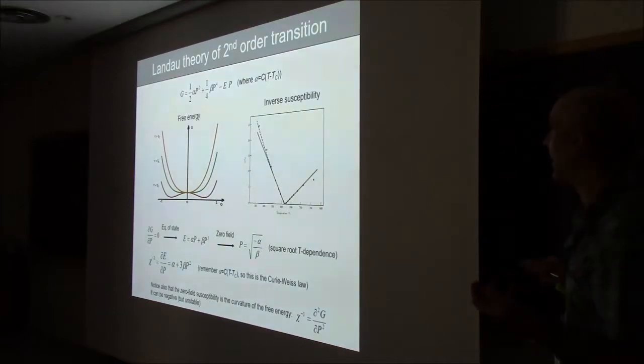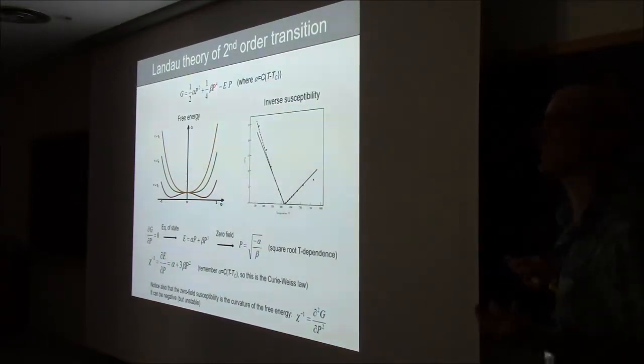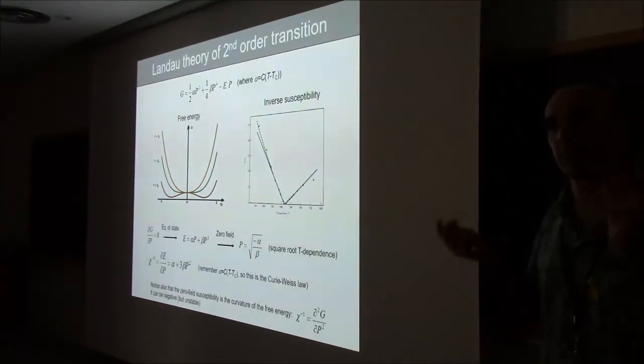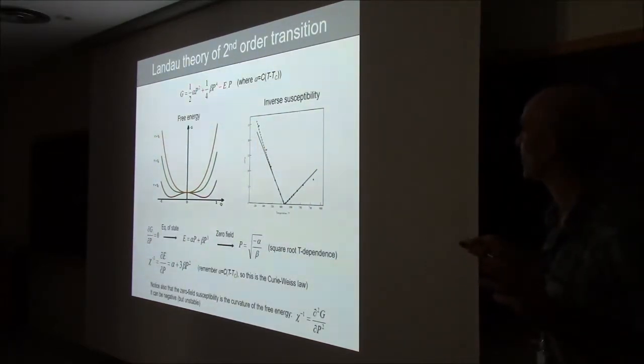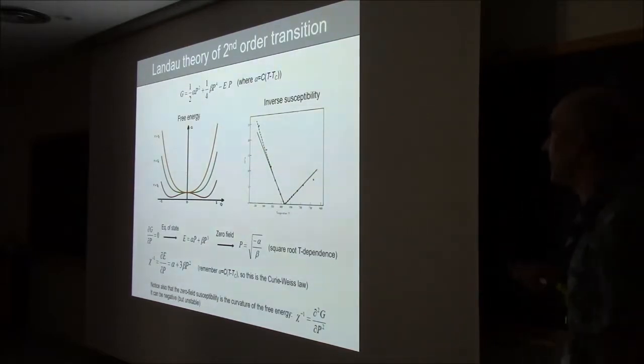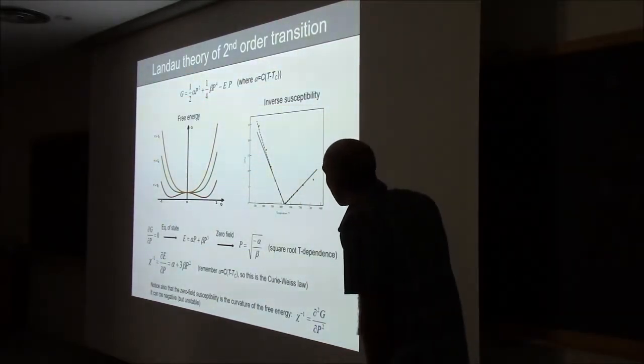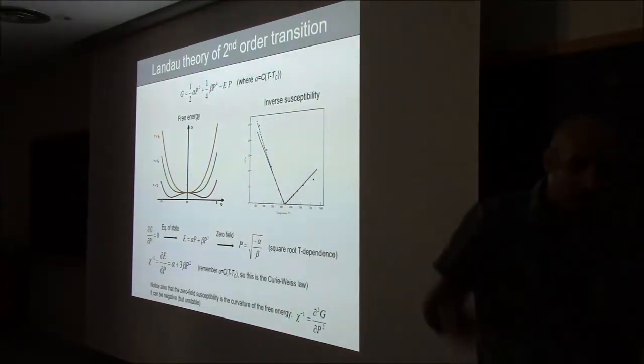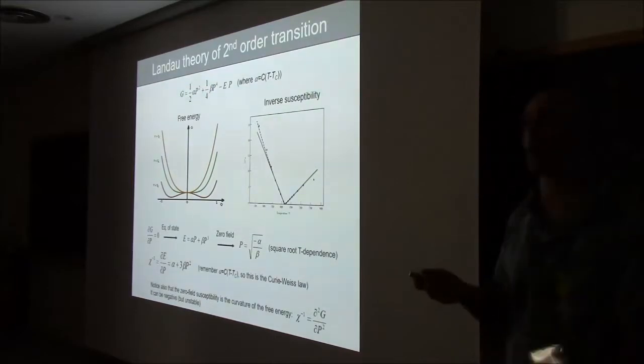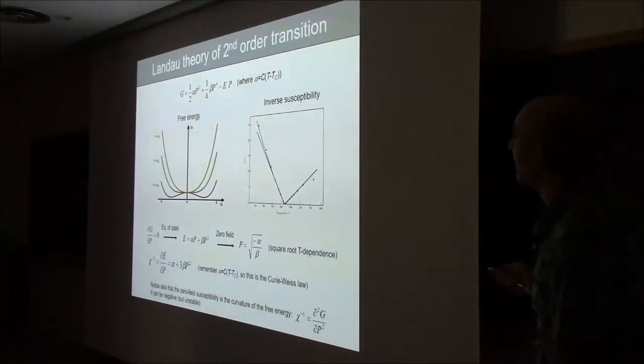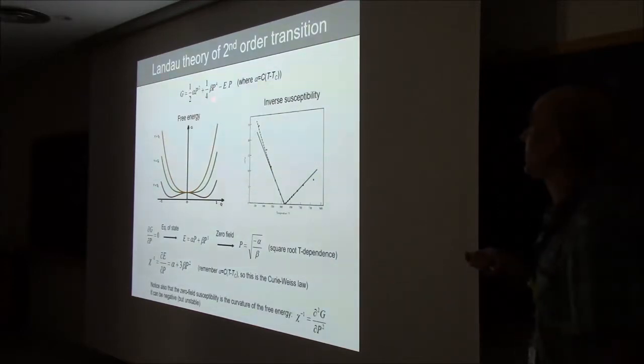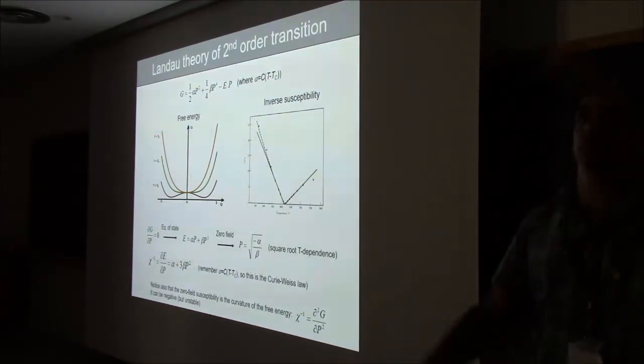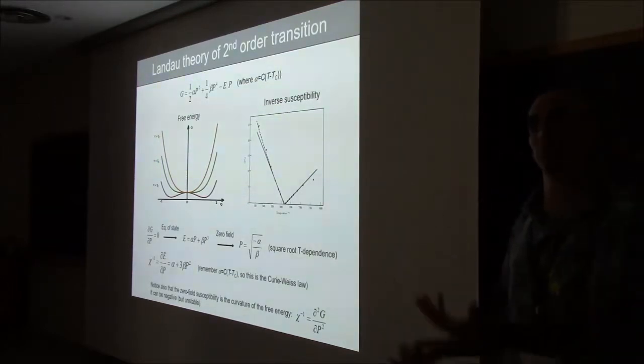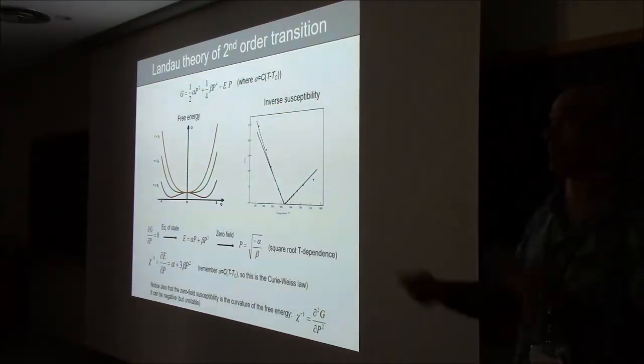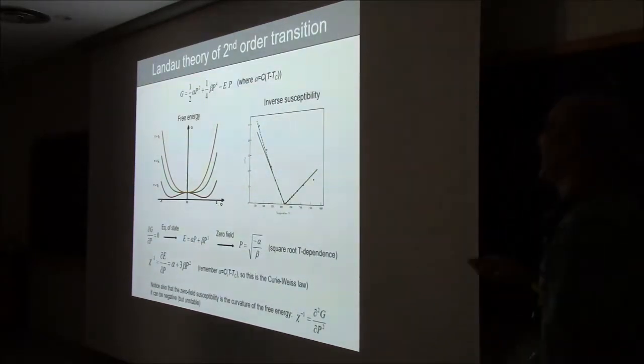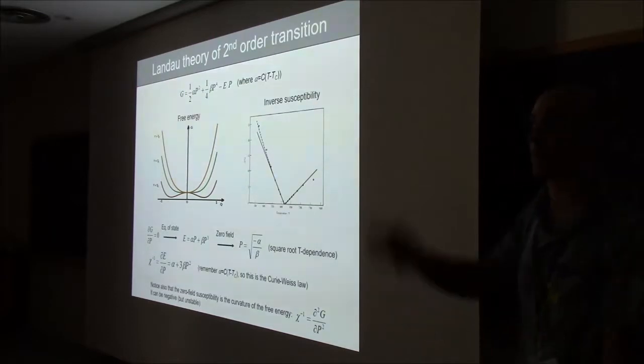So this is more or less how it works. It's a Taylor expansion, and the powers that you put here and the signs come from symmetry considerations, and this comes from energy considerations. Even the sign of these things comes from thermodynamic considerations. Imagine for a second that beta was negative. Then my energy would get lower and lower as I make the polarization bigger and bigger, which means the energetically most favorable state would be having infinite polarization. Basically, my material would explode. So that's not going to happen. We need beta to be positive for a second order transition.